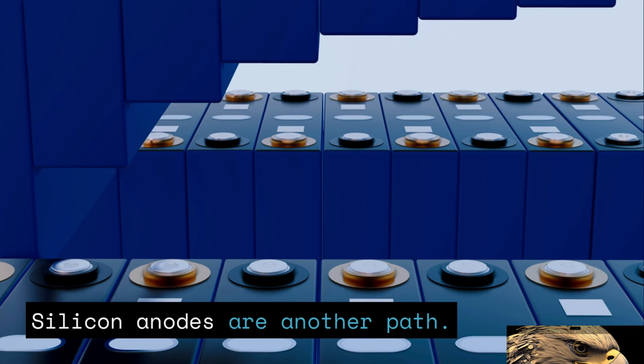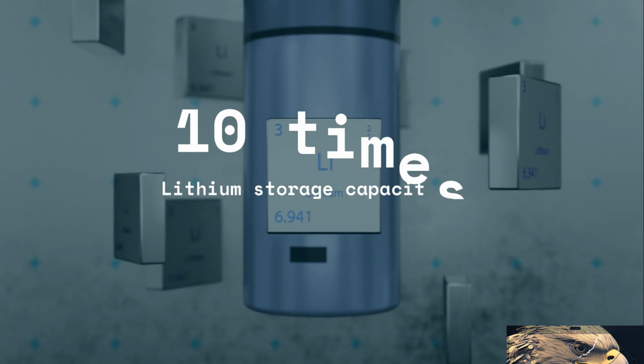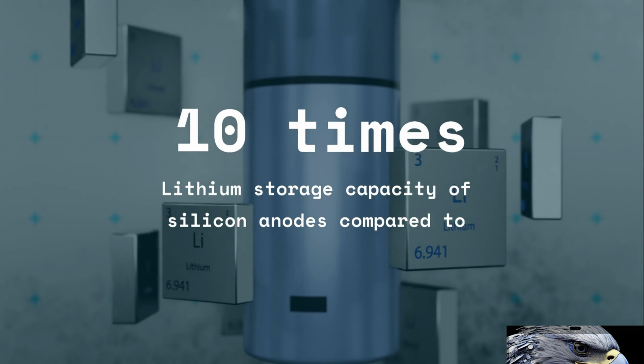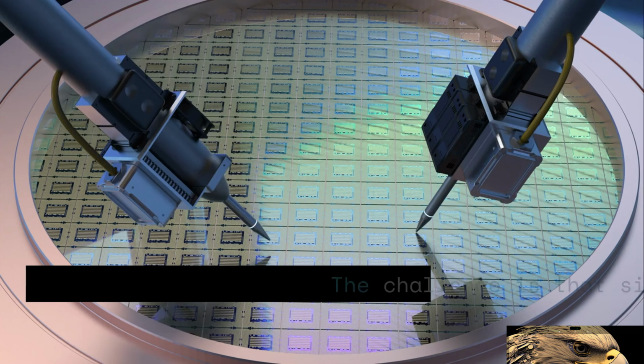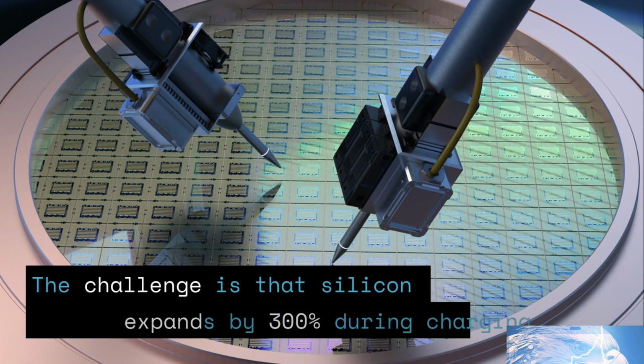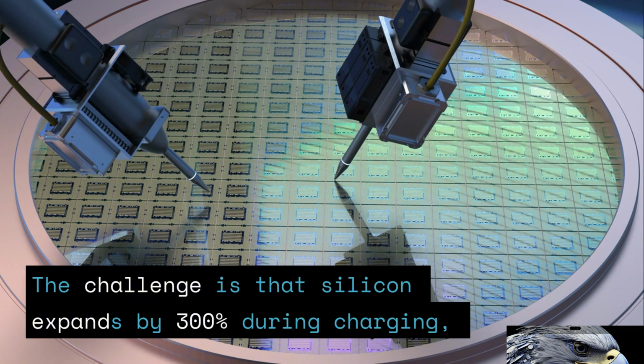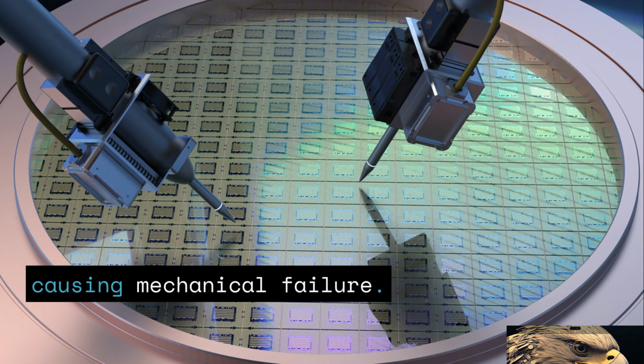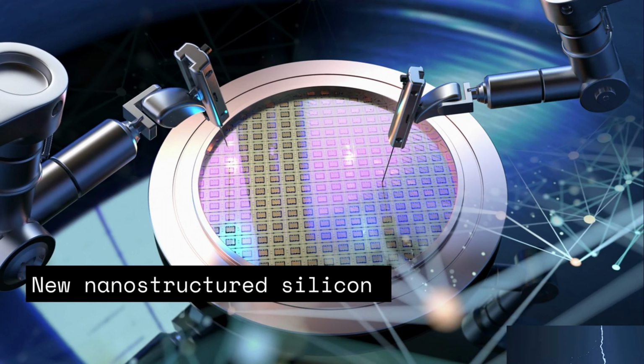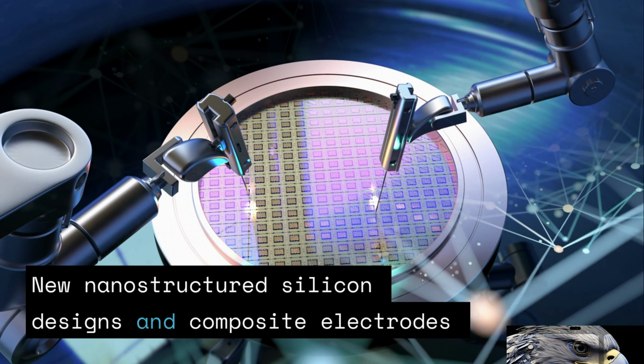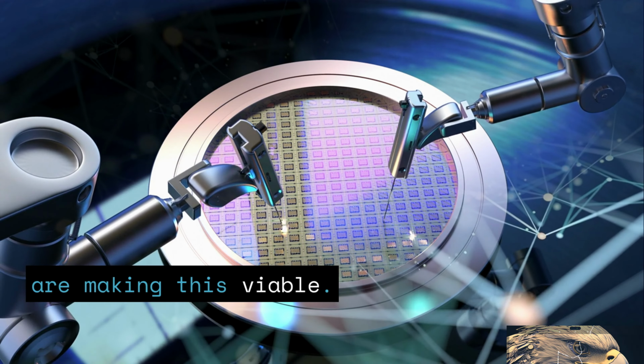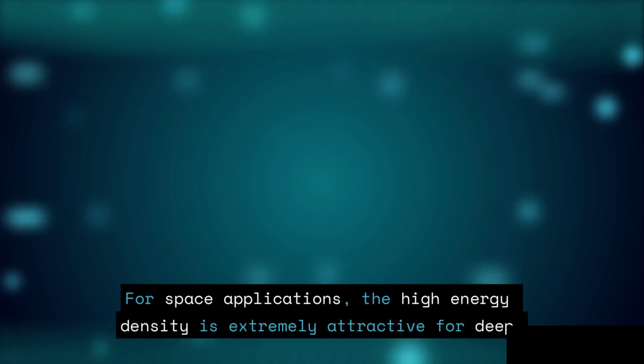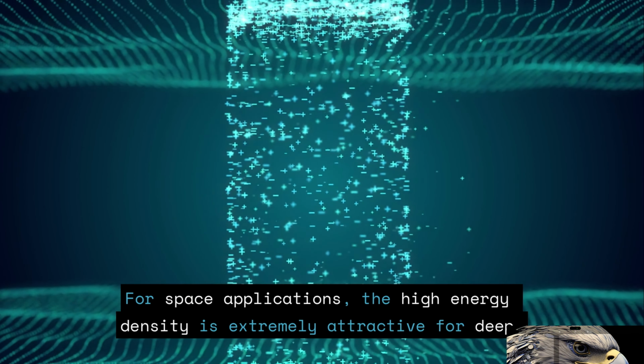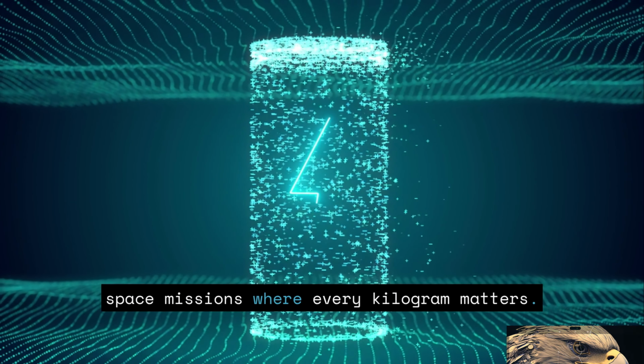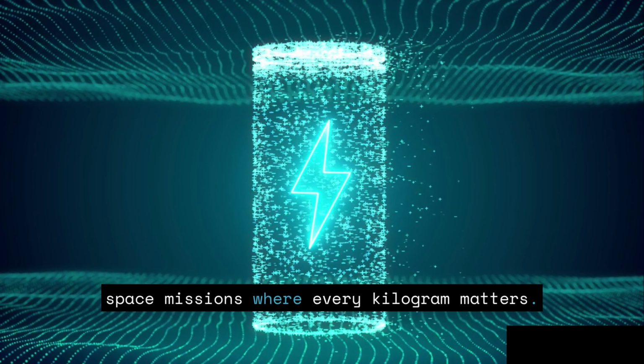Silicon anodes are another path. Silicon can store 10 times more lithium than graphite. The challenge is that silicon expands by 300% during charging, causing mechanical failure. New nanostructured silicon designs and composite electrodes are making this viable. For space applications, the high energy density is extremely attractive for deep space missions where every kilogram matters.